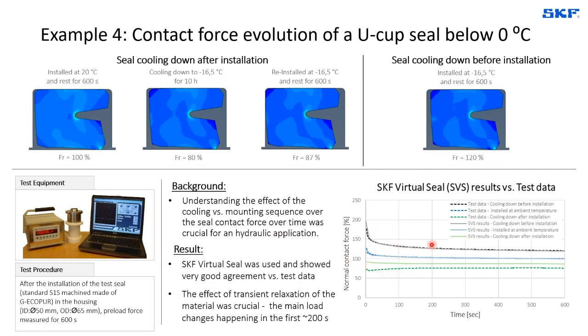And here we have basically the response in the dashed line of the actual test measurements at minus 16.5 degrees centigrade versus the actual SKF virtual seal results. And then we can clearly see that there is quite a good agreement between the test data and the model prediction again, despite the cold temperature that goes below zero.